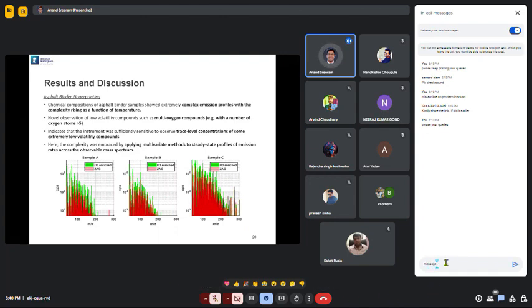In terms of bitumen fingerprinting, we could see that the chemical compositions of bitumen samples showed extremely complex emission profiles, with the complexity rising as a function of temperature. We were able to observe a number of low volatility compounds such as multi-oxygen compounds, that is, compounds with more than 5 oxygen atoms, which shows that the instrument was sufficiently sensitive to observe trace level concentrations of some extremely low volatility compounds. And again, we embrace this complexity by applying different kinds of multivariate methods to study the emission profiles of these bitumens in terms of the entire mass spectrum.